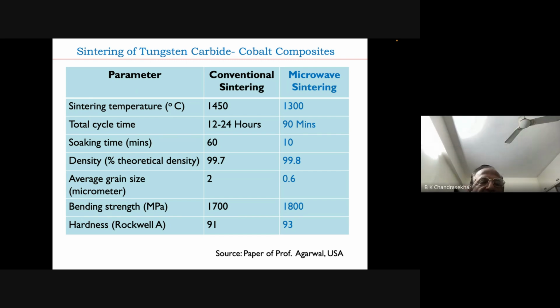So in this particular case, if the sintering temperature, maximum temperature, is 1450 degrees centigrade, soaking time means we reach 1450 degrees centigrade and keep it for 60 minutes. That is called the soaking period. Soaking time, and in this case it is 60 minutes.